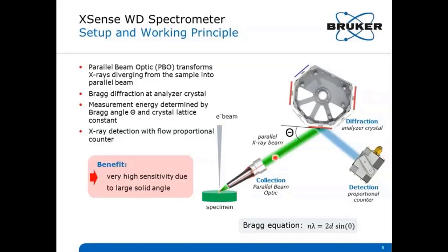The resulting X-ray beam is parallel, and this parallel beam hits one of the flat crystals here where Bragg diffraction occurs. Here are up to 6 crystals on the turret. Only photons of certain energy fulfilling the Bragg conditions are reflected towards the proportional counter, which is used for X-ray detection.